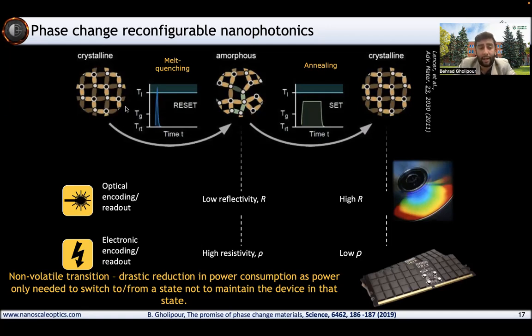So the phase change functionality that is at the heart of what I keep mentioning here is as follows on an atomic level. These materials can switch between a crystalline and an amorphous lattice. This can be induced optically or electronically, or even through thermal means. In the crystalline lattice, we have a very ordered lattice, so there's long range order in this lattice. In the amorphous phase, you generally have short range to medium range order, and this manifests itself as a drastic change in reflectivity and resistivity.